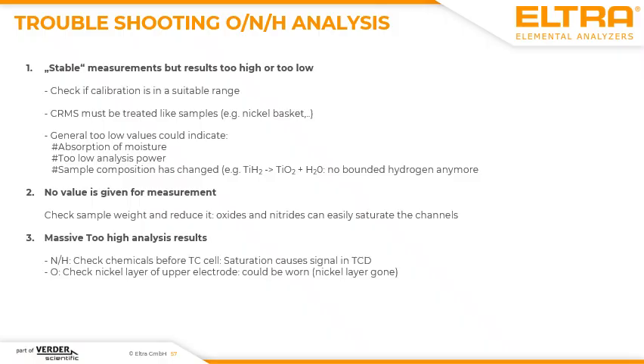caused by a saturation of the chemical filter which is sitting before the TC cell. When this chemical filter is saturated, you will also get immediately very high concentrations for nitrogen and hydrogen. When you only get this kind of very high concentrations only for oxygen, then it's recommended to check the upper electrode because some samples could be very